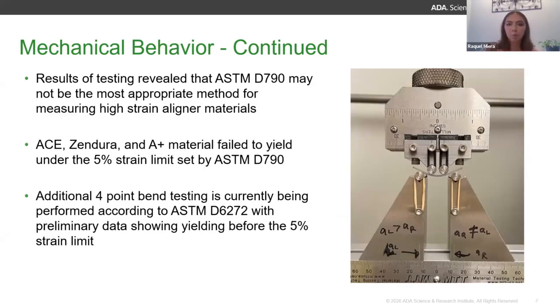The results of this mostly revealed that ASTM D790 is probably not the most appropriate method for measuring these high strain aligner materials. The ACE, the Zendura, and the A+ all failed to yield under the 5% strain limit set by ASTM D790. Which meant that some of the assumptions that standard makes are probably not giving us the most accurate results for those 3 materials. We want to do additional 4-point bend testing, which we are currently doing according to ASTM D6272, and our preliminary data is showing that these specimens are yielding before that 5% strain limit, but they are getting pretty close to the 5% strain limit.